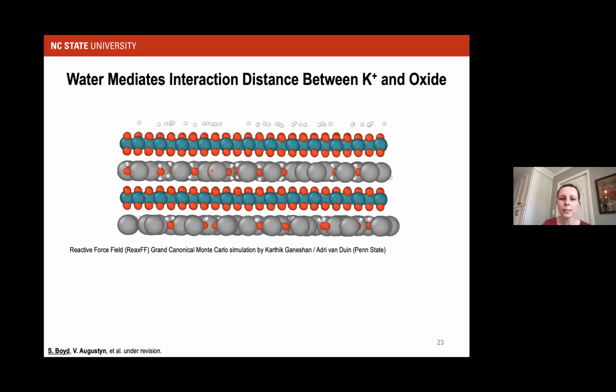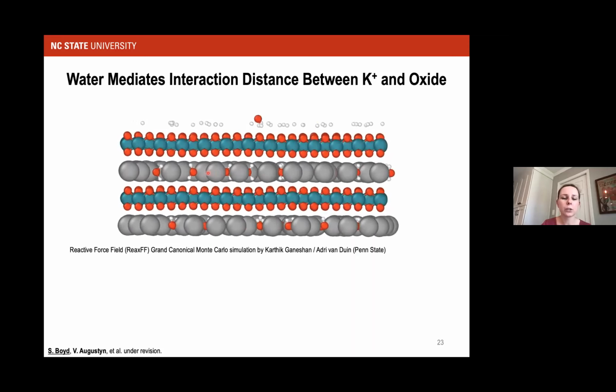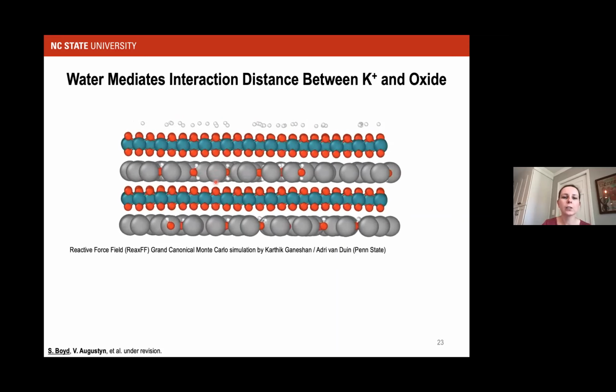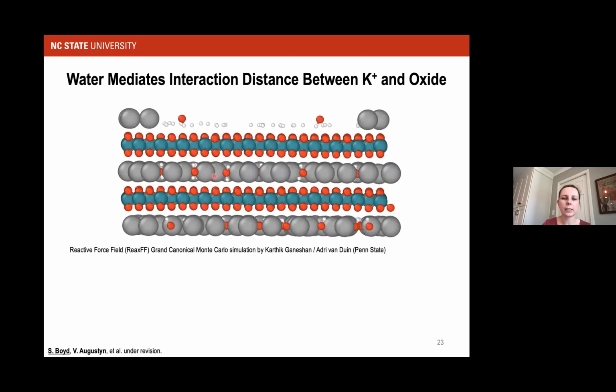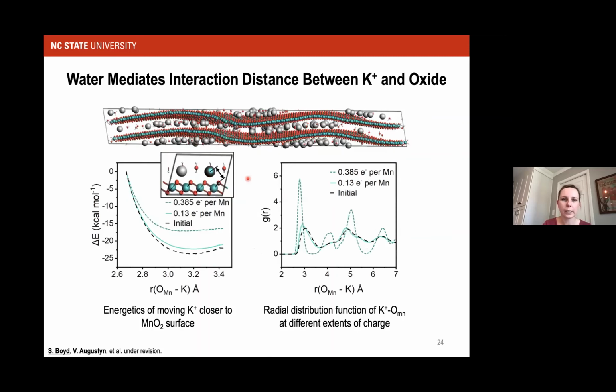And you can see that the potassium ions are pretty much in the middle of the interlayer. They have no particular affinity towards either surface. They're not really sticking to either surface, and the water is surrounding them or coordinating them. Some other details that these simulations reveal that we haven't been able to verify experimentally but look really cool is that there's wrinkling of the sheets when there's some local inhomogeneity of the potassium insertion. So depending on exactly where the potassiums are, you see this kind of wrinkling occur to, I guess, accommodate the stress.